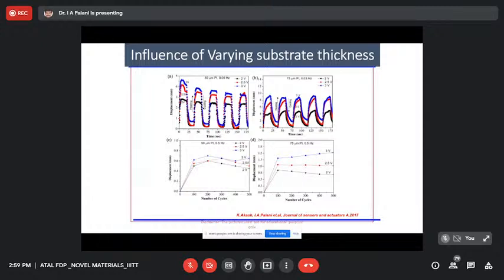See whether I am getting the same results throughout, even if I go for more than 1 lakh cycles. Okay, because here you may ask me a question. It is a deposition on a polymer, so there is a chance that the more we actuate, the film may peel off from the surface. But the interesting part is, since we are doing the deposition completely in a vacuum environment, in a controlled atmosphere inside a thermal evaporation unit, we could observe that even after 1 lakh cycles, the removal of the material was not happening.